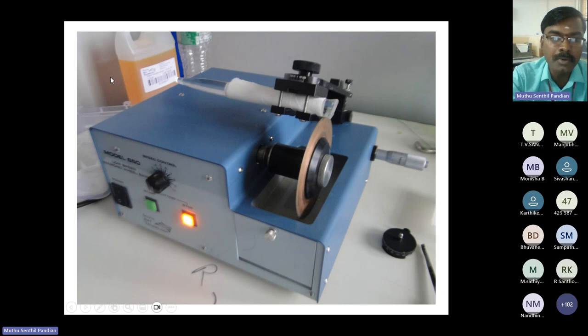So this is the diamond powder wheel cutter, which we have with support from DAE BRNS. Before we go for the crystal cutting, you have to measure the mechanical stability of your grown crystal using Vickers microhardness measurement, to see whether your crystal is mechanically low, moderate or very highly stable material. Depending upon the mechanical stability of your material, you can increase or decrease the speed of the diamond coated wheel cutter. And ethylene glycol is kept inside this tray, and ethylene glycol is used as a coolant.